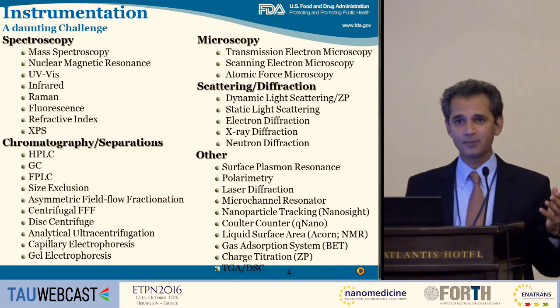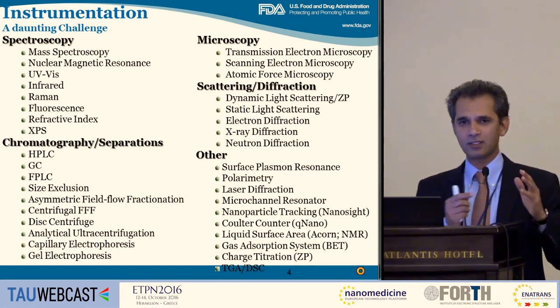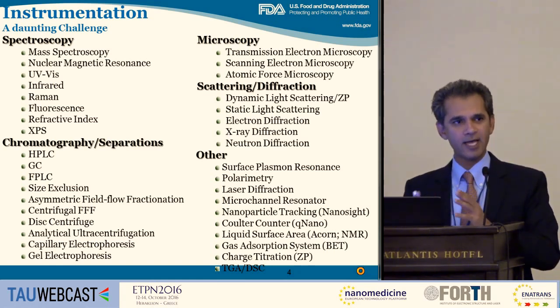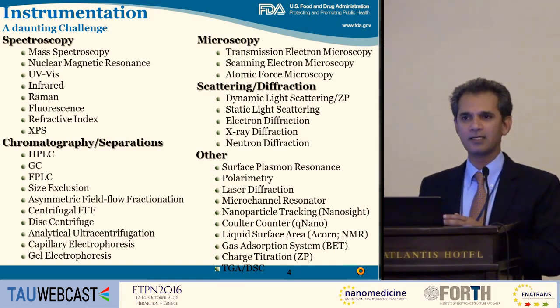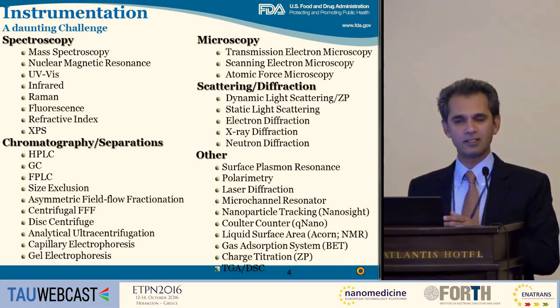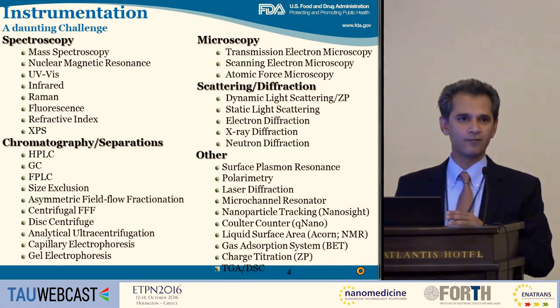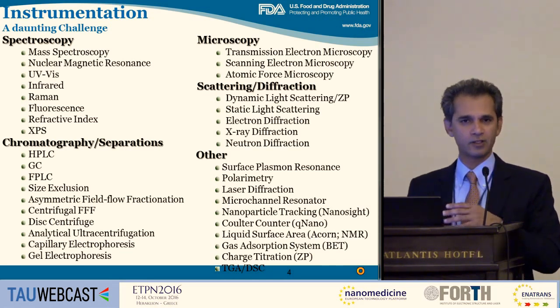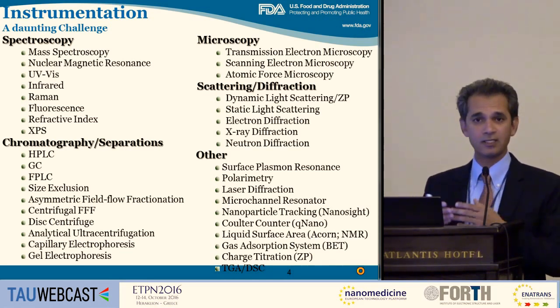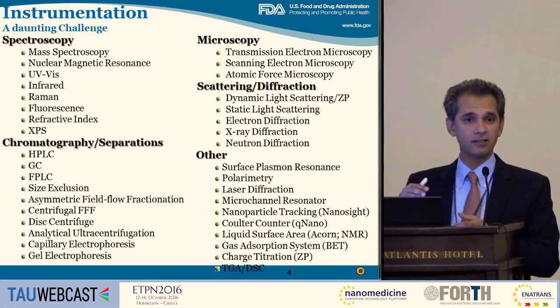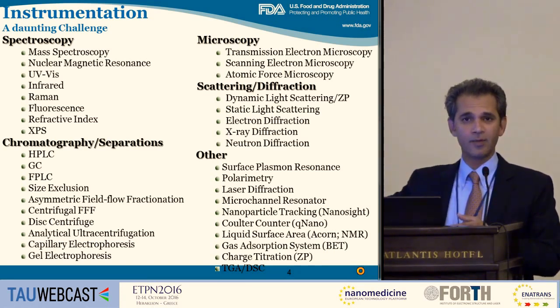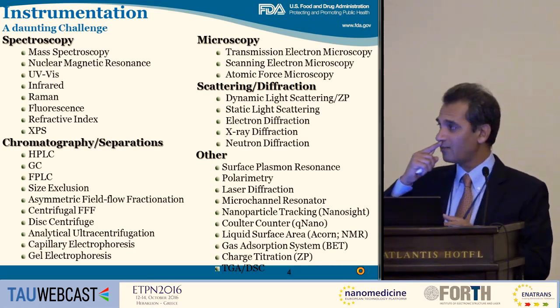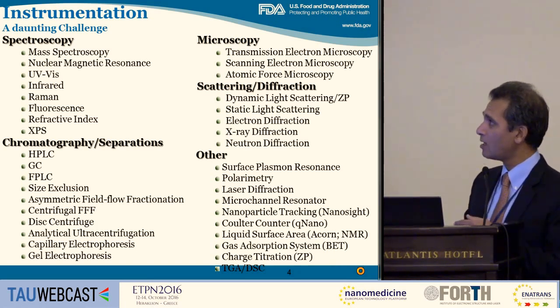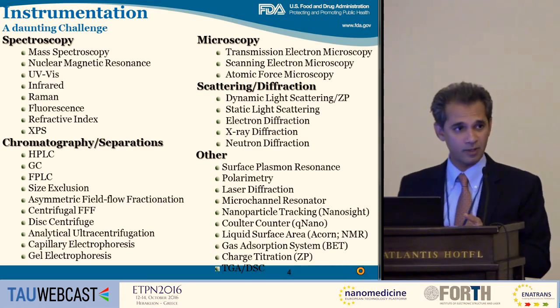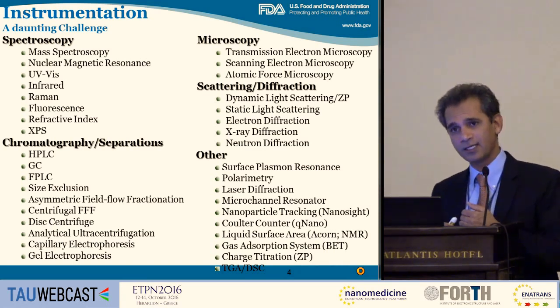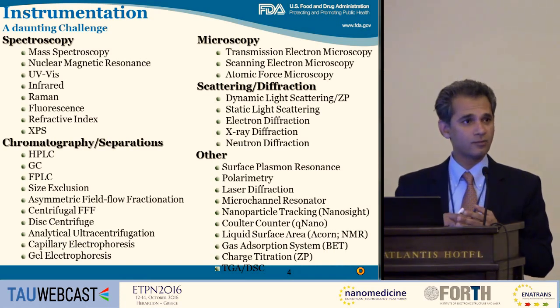That size polydispersity is very complex. And if there are slight differences in the size, a batch mode measurement does not necessarily detect those changes. It is not sensitive enough. So that's where you have to go through either a fractionation method such as field flow fractionation, size exclusion chromatography, and other kind of methods to look at the polydispersity in the sample. And depending on how you measure, not only you measure and then the instrument spits out a number, but then it depends on whether you are looking at a Z average, the intensity, the volume, or the number.